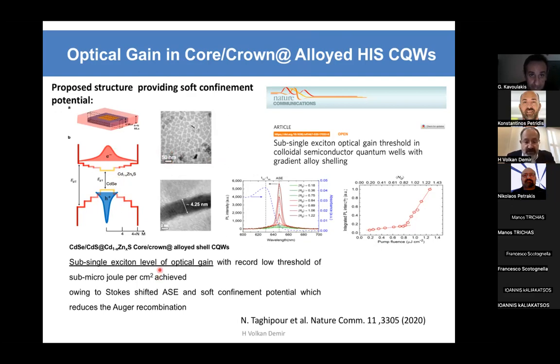observe in the film, this is now solid state, a sub-single exciton level for the threshold. Still, we have biexcitonic gain. Statistically, obviously, part of our colloidal quantum wells in the ensemble actually pushed into a population inversion with 2 excitons per particle, but it suffices to use only part of them in the ensemble. And on the average, because we are using only part of them, per particle of the whole system in the ensemble, we can actually have sub-single level of threshold.